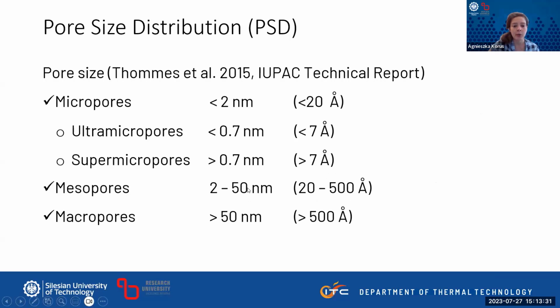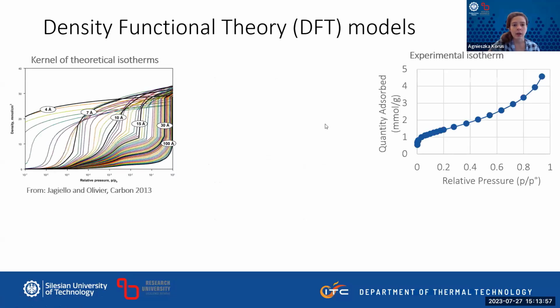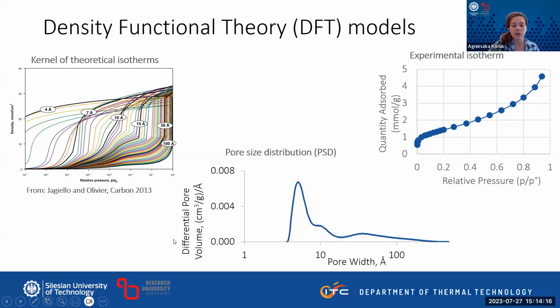So just to briefly remind you about the pore sizes that are distinguished based on the IUPAC report. With the micro and mesopores, this is the area that we are interested in. We measure it with gas adsorption methods. We are especially interested in super micropores and in the smaller mesopores because these were supposed to be the most important ones for ion adsorption. And to determine them, we've been using DFT models, which basically rely on fitting the gas adsorption isotherm that you experimentally measured with theoretical isotherms, with numerical methods and a regularization procedure. You can obtain the representation of the pore distribution in your samples.